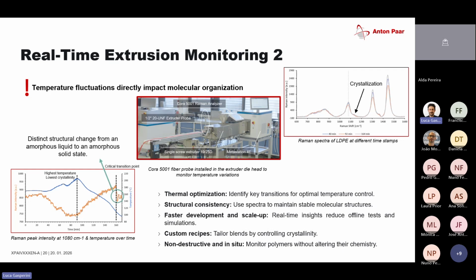And what's obvious is that if I have a very high temperature, then the crystallinity will be lower. But if we take a look here, we were decreasing the temperature over time, and at some point here, the crystallinity dropped, even though the temperature went down. So there again, you can see a critical transition zone. So you can understand how your polymer melt behaves on a crystalline level during extrusion.